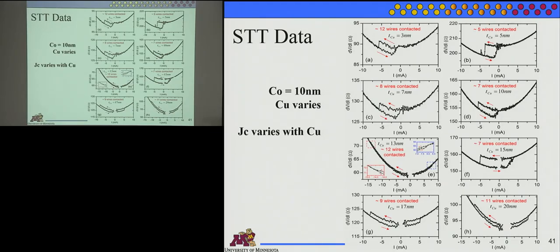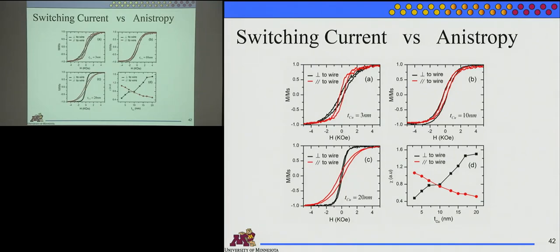We want to be able to switch it with a low current and have it stay in the 1, and then switch it with a low current and have it stay in the 0. So using positive and negative current, we want to be able to store 1s and 0s. But the nice thing is, remember we have 10,000 times aspect ratio. We could grow this material, then that material, then that material, all in one nanowire and have 3 states in 1 bit, which would be very handy for high density.